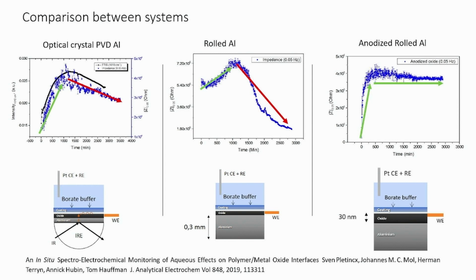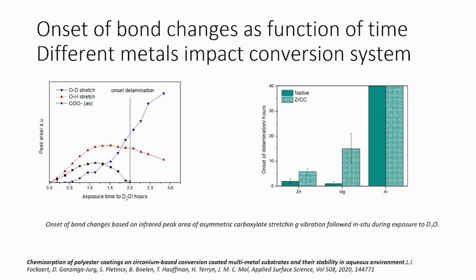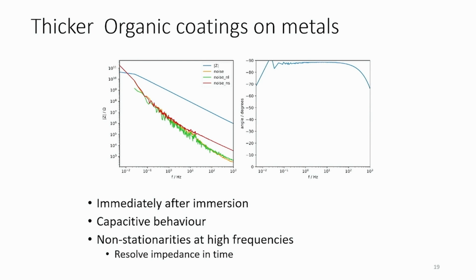The infrared allows you to follow a little bit how it is happening, in the impedance measurements compared to infrared measurements. If we now go to other systems, we actually worked on zinc, magnesium, and aluminium. This we did together with Tata Steel, because they are working with zinc interfaces, aluminium interfaces, and magnesium interfaces. You can follow the stability of certain bonds as a function of time with the infrared measurements or with the impedance measurements.